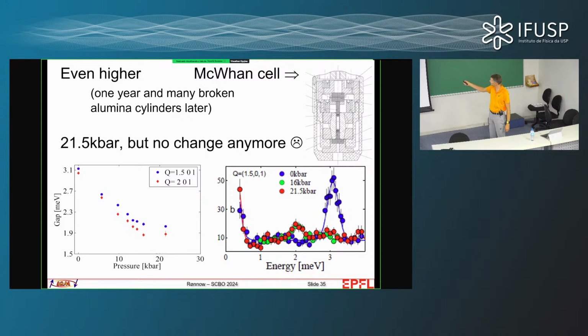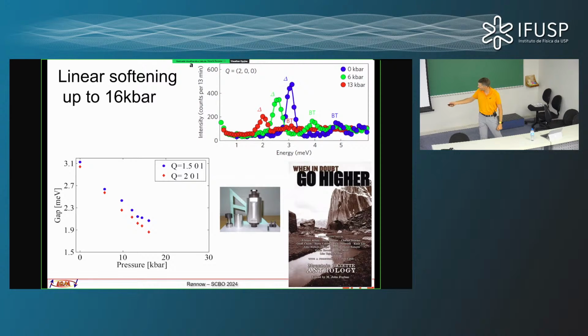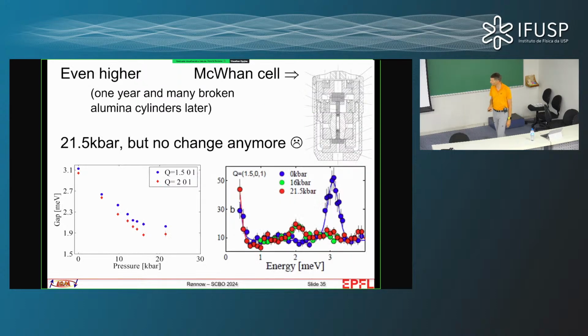So here's a McWhan cell, which is very complicated to operate. Took a long time to get this experiment to work. We managed to go from 16 kilobar all the way up to 21 kilobar, and we're really looking forward to seeing the gap going even further down. We had even made some very optimistic predictions that this actually would accelerate and go faster at some point. Then we did the experiment, and basically from 16 kilobar to 21 kilobar, the peak did not move at all.